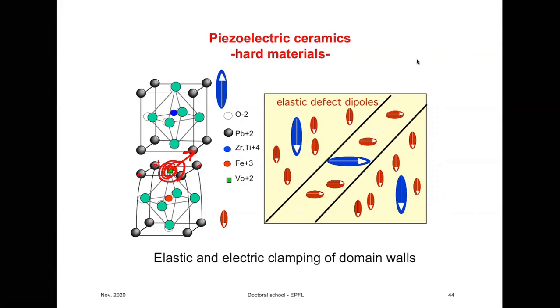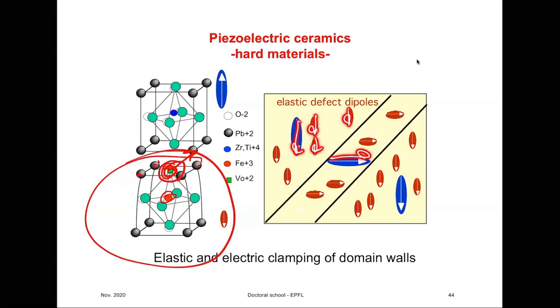Here it is drawn as though the lattice will shrink in that position, but I think it's actually the opposite. It will expand. I think that's the case. In any case, all these defects, the unit cells in which there is a defect, will also be elastic dipoles. Okay, they will elastically deform the space. So not only do we have here polarization of dipoles and ferroelectric distortion of the cell, but we also have elastic dipoles.